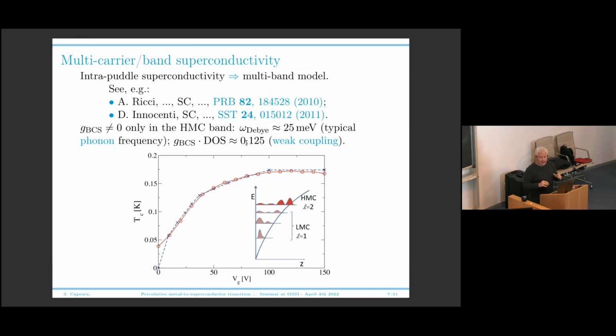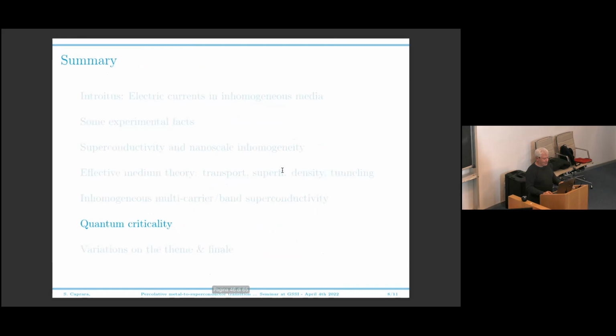And the idea, I will tell only the idea, is that remember, there are low mobility carriers. They are a lot, but the system is not superconducting when you have only low mobility carriers. The system becomes superconducting when you introduce some high mobility carriers. So imagine now that at the interface, you form several subbands because your two-dimensional electron gas is confined in some potential well. Then you have the subbands that host the low mobility carriers. And when the chemical potential is there, you have no superconductivity. Once you reach the band that hosts the high mobility carriers, you start seeing superconductivity. And then that fits the data very well, and you have superconductivity inside the high mobility carrier band without the necessity to claim that superconductivity is strong coupling or something very weird. It's weak coupling, BCS superconductivity.